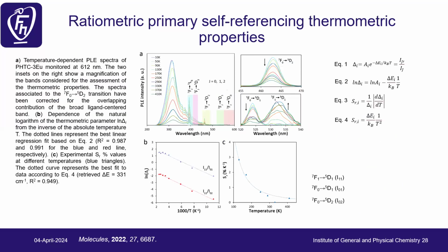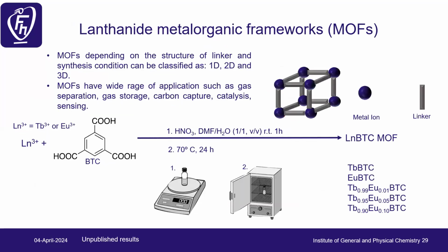And we got quite good sensitivity, about 1.3, sorry, around 3-4 at 100 degrees Kelvin, and then dropping down to 0.6. I forgot now by heart, but this is quite interesting. Another way how you can utilize the lanthanides for the thermometric properties.